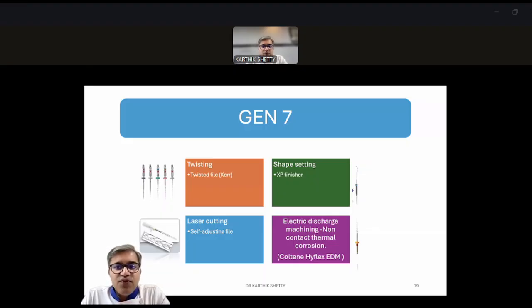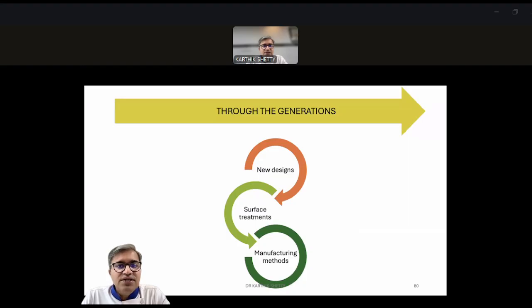As I mentioned earlier, if you want to avoid grinding, the only way to avoid creating micro imperfections or micro cracks on the surface of nickel titanium, which may be the genesis of failure at a later point in time and may reduce your cyclic fatigue values, you would want a non-contact method of manufacture. That would be the ultimate, which has been achieved with this particular file system, HyFlex EDM, and that is why this file gives you a very, very high degree of durability, because it does not have those micro imperfections on its surface.